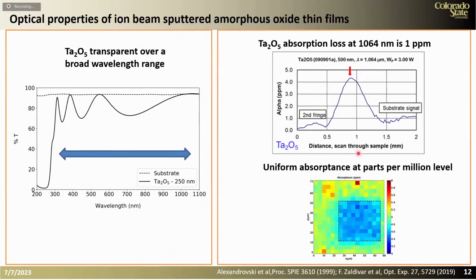And these films, as I mentioned at the beginning, can achieve impressively low absorption loss at around 1064 nanometers. The LIGO work has shown that in mirrors that have about 50 layers, one can achieve an absorption loss at 1064 nanometers that is less than 1 part per million.